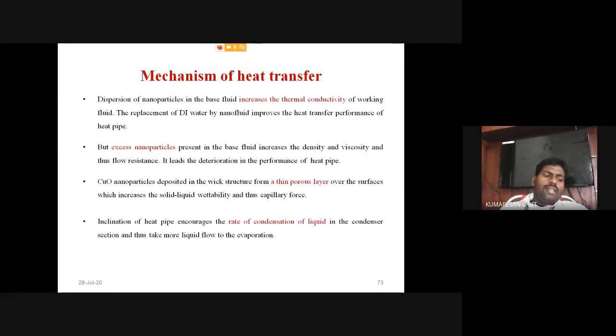That's why the heat pipe filled with the 1.5 weight percentage deteriorates the performance of the heat pipe. Then copper oxide or aluminum oxide nanoparticles deposited over the wick structure form a thin porous layer over the surface, which increases the solid-liquid wettability and also increases the capillary action.